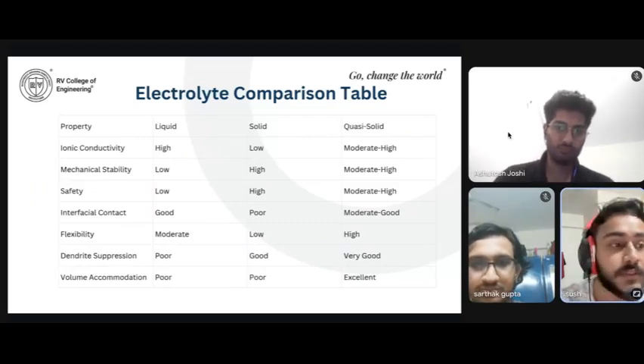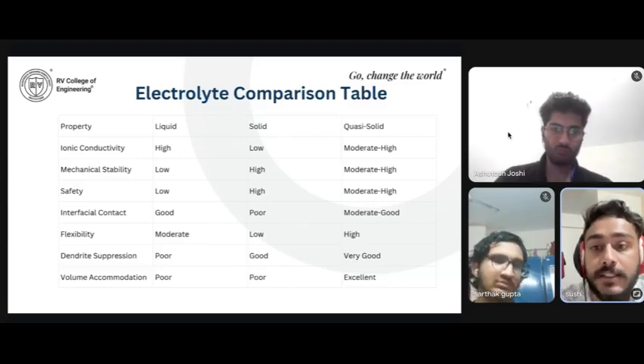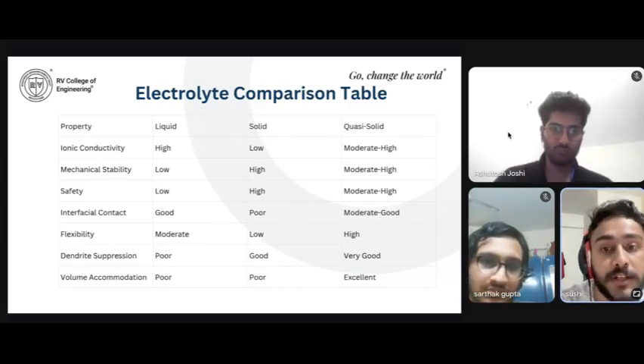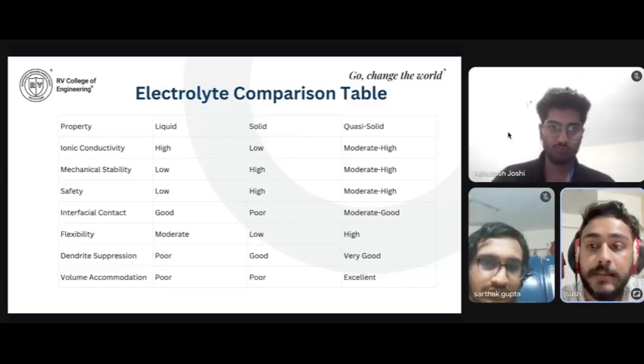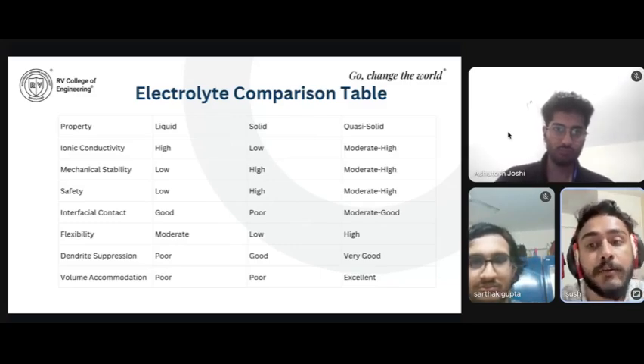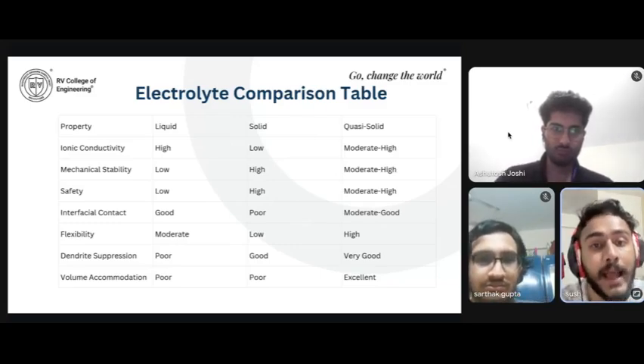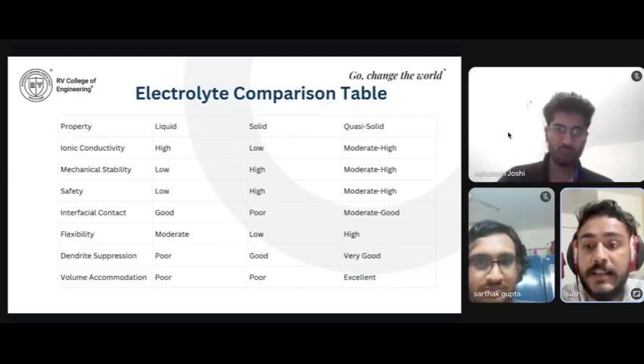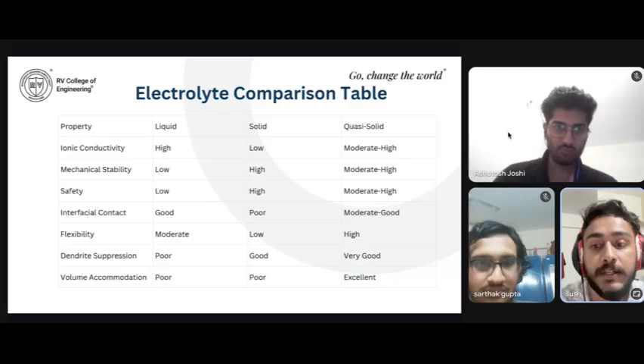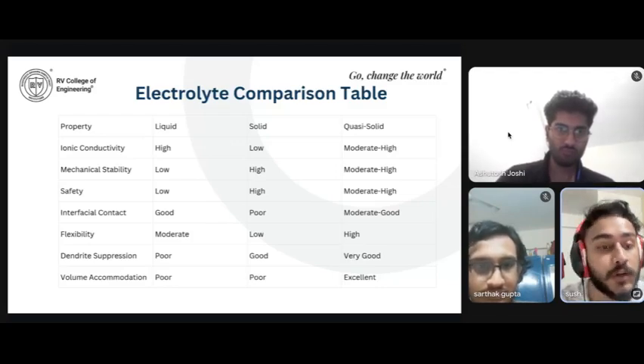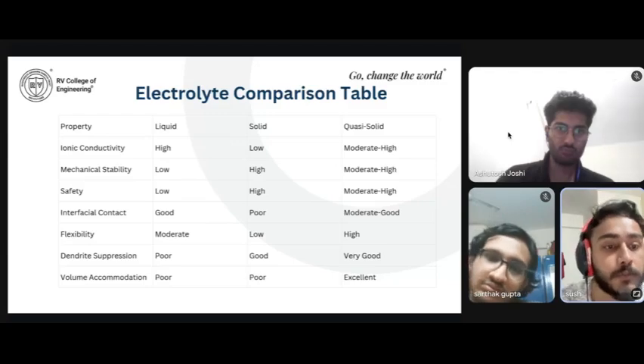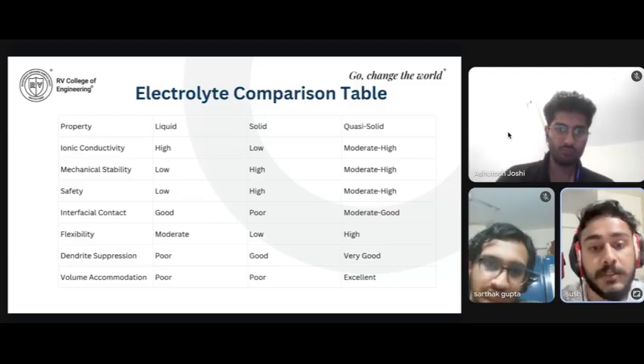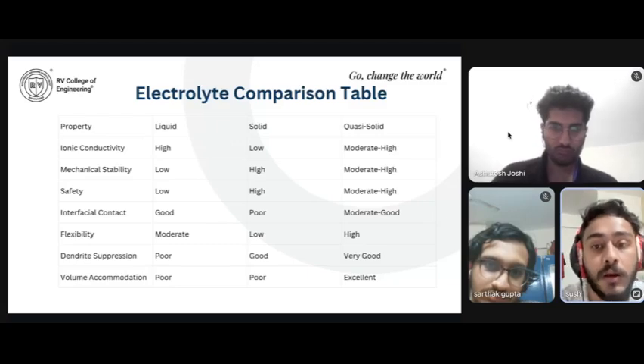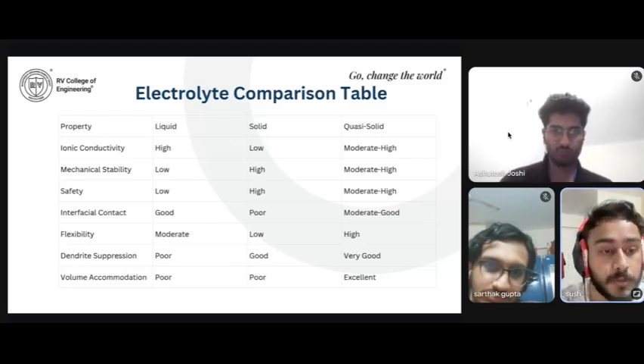So now let's compare the three different types of electrolytes, that is the liquid, solid and quasi-solid. Here we can see the ionic conductivity. Liquid electrolytes have high ionic conductivity whereas solid has low, and the quasi-solid ranges from moderate to high. The same is the case for mechanical stability, where liquid electrolyte mechanical stability is low, solid is high, and the quasi-solid is from moderate to high. If we talk about flexibility, liquid electrolytes provide moderate flexibility, solid provides low flexibility, whereas quasi-solid provides high flexibility. When we talk about dendrite suppression, in quasi-solid dendrite suppression is very good, solid provides good dendrite suppression, and liquid provides poor dendrite suppression.